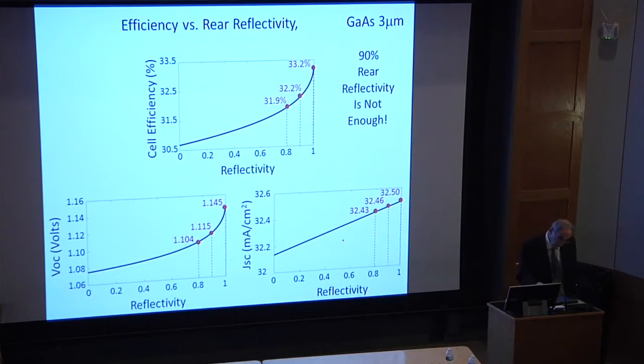So what happens if you, for example, look not at the luminescence efficiency internally, but rather the rear reflectivity, because it's also a mirror. You need a very good mirror, because you're going to be reflecting many times. And here's a statement that 90% reflectivity is not enough. And here's sort of an example. If you make the rear mirror more reflective, it gets more and more efficient. But a lot of the improvement gets really steep, well above 90% reflectivity. So you don't get much of the benefit until you're well over 95% reflectivity.